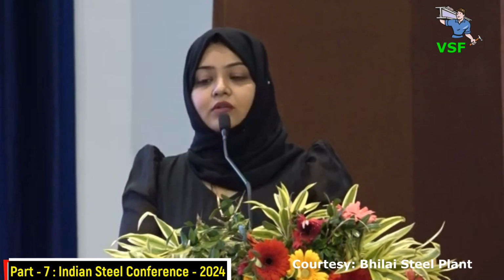Next important application is geopolymer concrete, which is 100% replacement of cement. Here we can see the binders are the fly ash, steel slag or metakaolin, red mud. All these are industrial byproducts. When activated with alkali activators like sodium hydroxide and sodium silicate, on mixing it forms a polymerization chain reaction, and on hardening and setting this forms a geopolymer concrete, which is equivalent to the conventional concrete made with 100% cement or a partial replacement of cement.